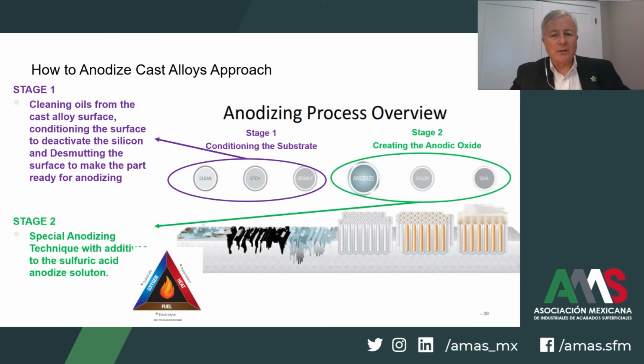Here, the oxide growth is enhanced and a continuous coating can be obtained. The silicon intermetallic particles are deactivated in stage 1, and then the chemical potential of the surface is changed. Bringing the chemical potential of the aluminum and the silicon together enables the anodizing process to continue more homogeneously over the part surface, where we get thicker layers.